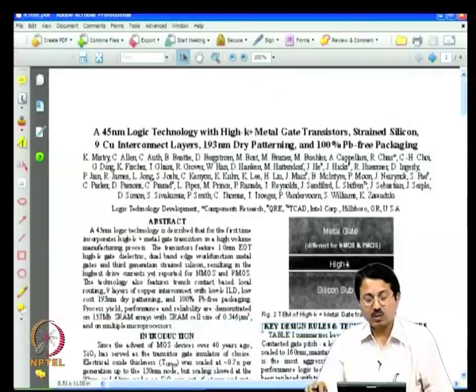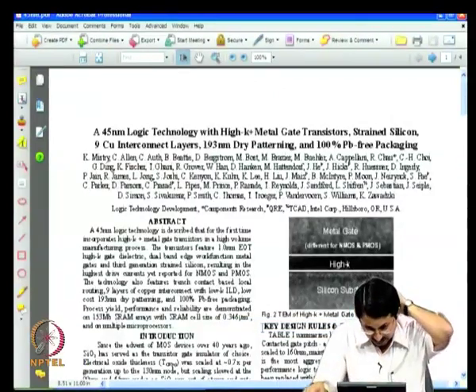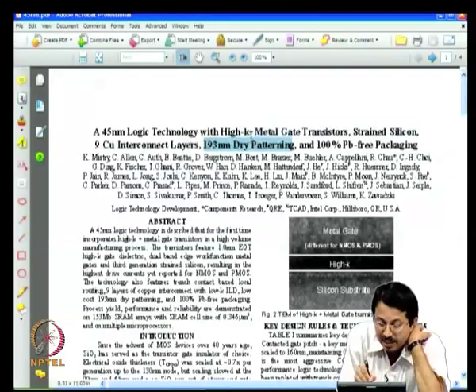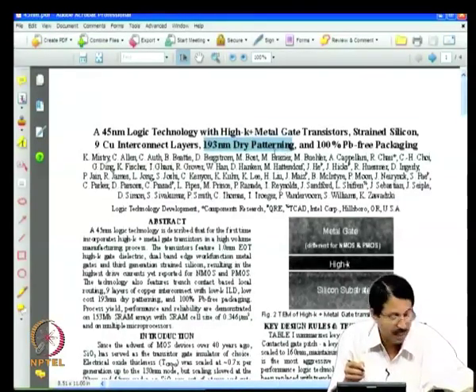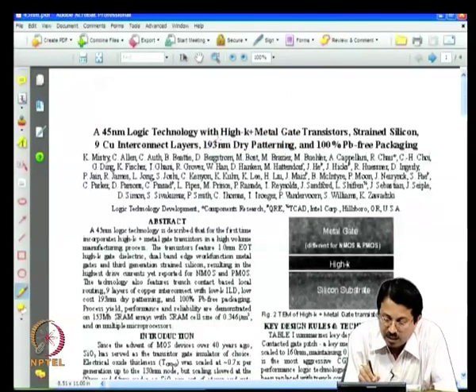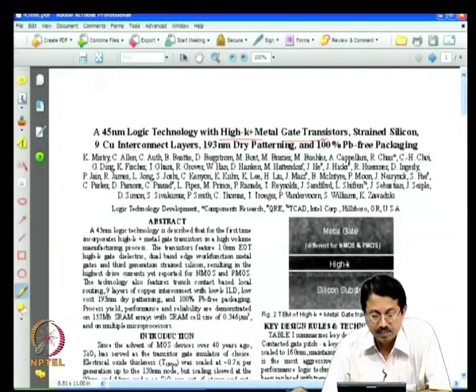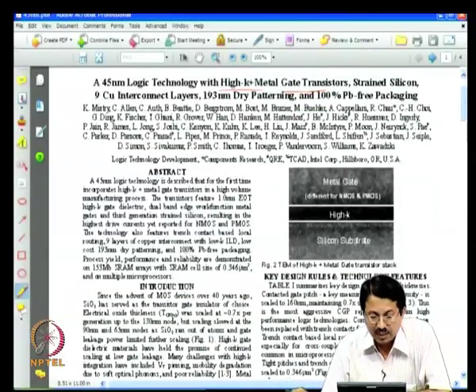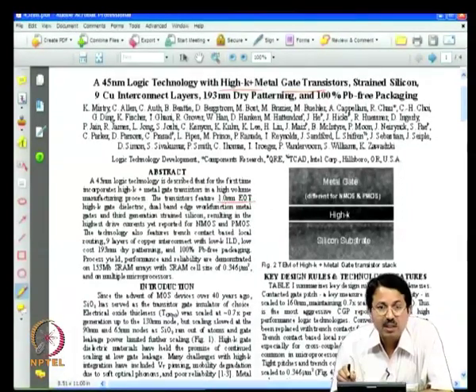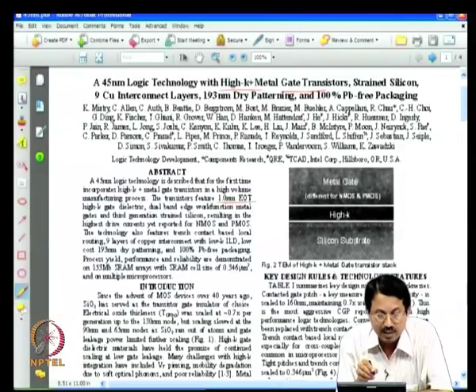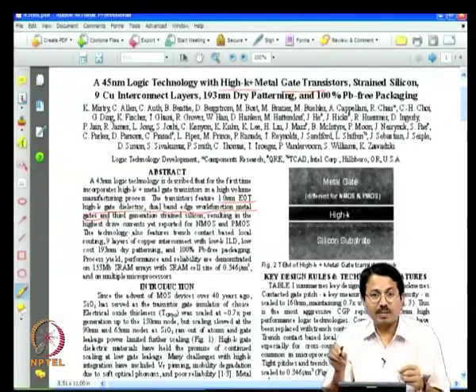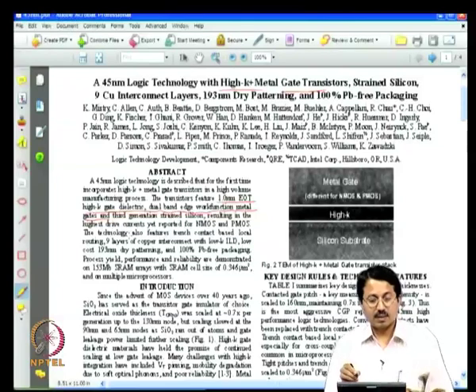Then at 45 nanometer you see a very significant departure. And what is that? For the first time you see high K gate dielectrics along with metal gate, high K metal gate for the first time. The 45 nanometer logic technology transistors feature 1 nanometer EOT, that is equivalent oxide thickness, but they actually use a hafnium oxide gate dielectric which is thicker than 1 nanometer. They use a high K gate dielectric and dual band edge work function metal gates, 2 different metals, one for N channel and one for P channel transistors.